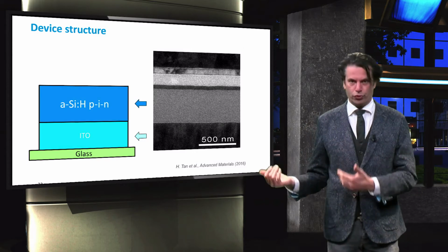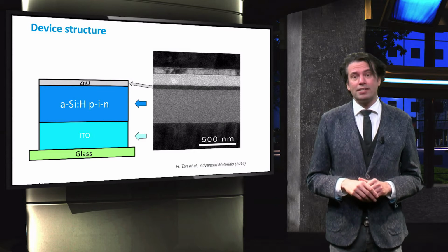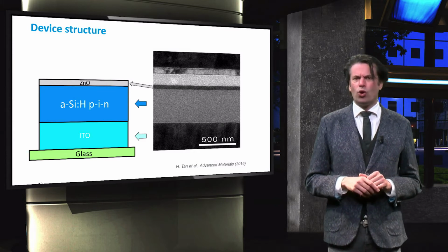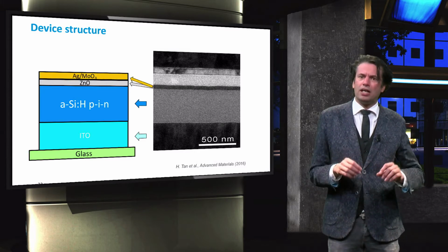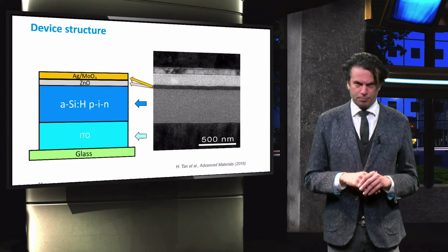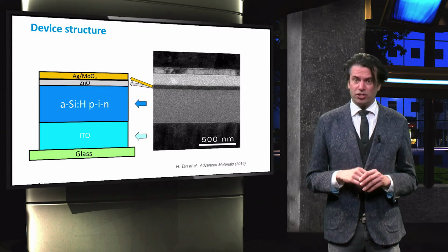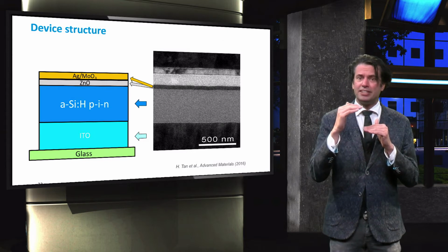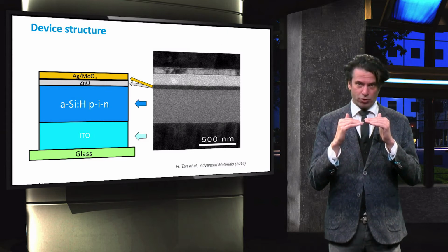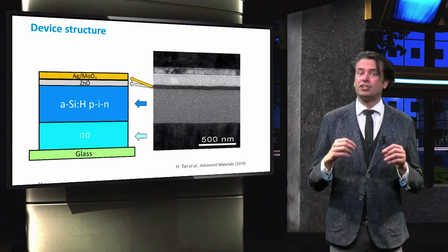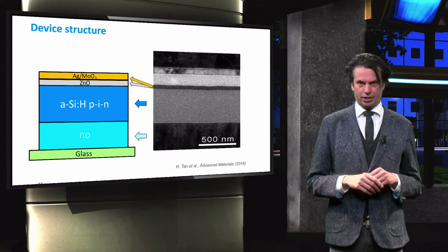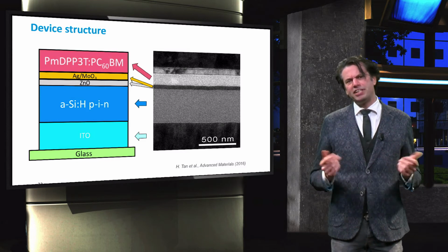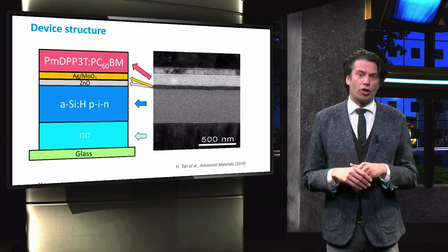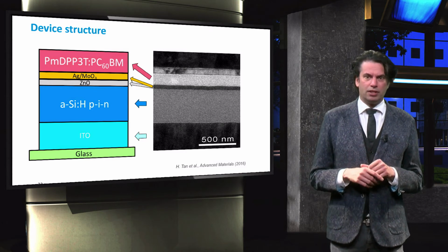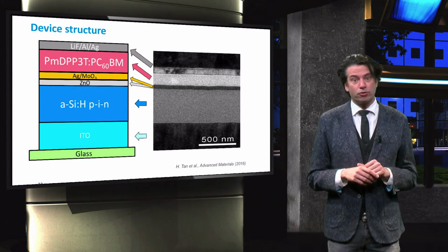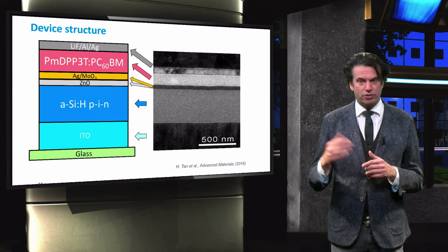The electron collecting layer is zinc oxide and the hole collecting layer for the bottom cell is molybdenum oxide. An extremely thin transparent silver layer is integrated between the zinc oxide and the molybdenum oxide. This layer has the functionality of a recombination layer. On top of these intermediate layers, the low bandgap organic material is deposited. Lithium fluoride is the electron collecting electrode just before the metal contact.